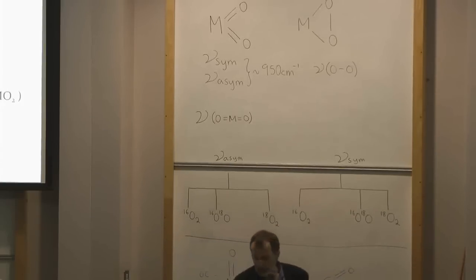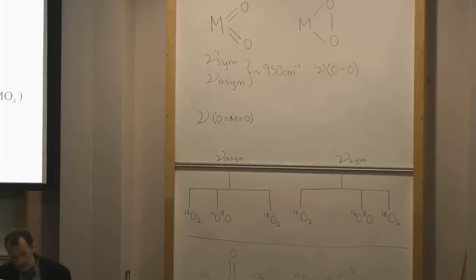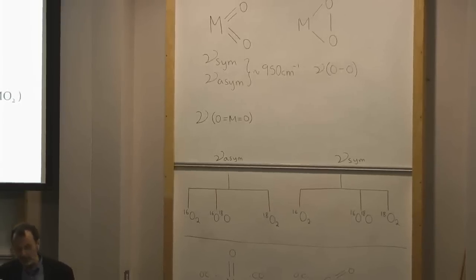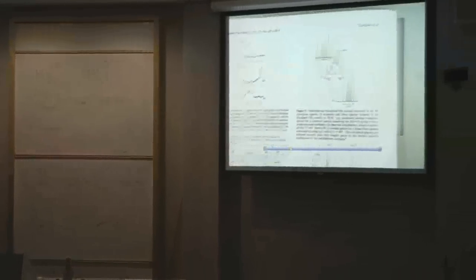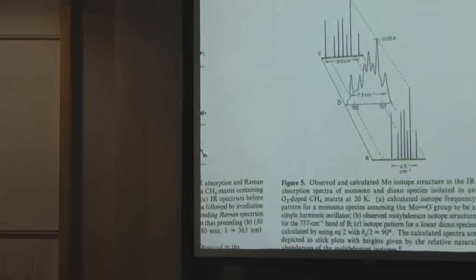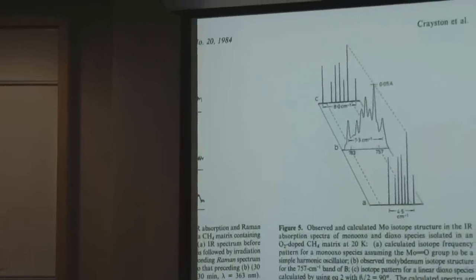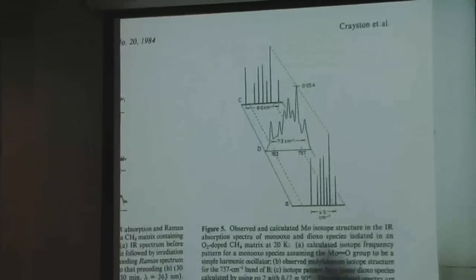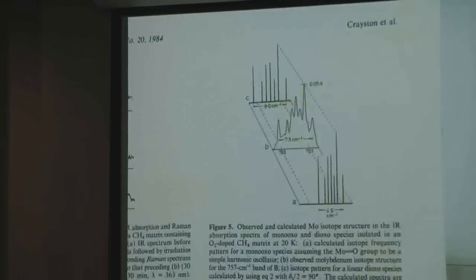So we had some success doing this, we published some work, we got some nice spectra. Probably the breakthrough in my PhD was when we actually saw molybdenum isotope structure on the asymmetric stretch of this molecule, and you could see that in the spectrum at the top corner there. The middle spectrum is our observed spectrum. And these little peaks that come out in here are due to the different isotopes of molybdenum. We needed a Fourier transform infrared spectrometer to do that.